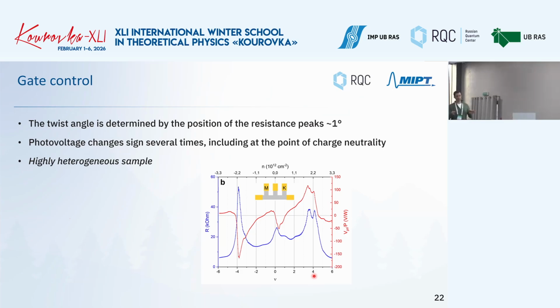So we get these correlated states, and we can move back and forth by changing the gate, and then we study what happens with the photovoltage. And it turned out that indeed something is happening in these areas where you can reach the correlated state.